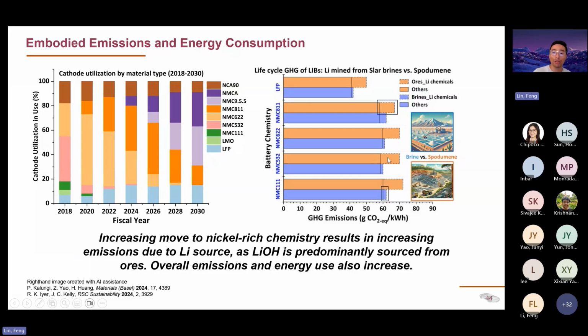But obviously, lithium hydroxide also contributes to more emission, because lithium hydroxide is predominantly sourced from ore, and the overall emission and energy use are higher than from other kinds of sources. So going for nickel-rich, we already have one penalty, the use of lithium hydroxide. If we can use lithium carbonate, that would be great. We are also trying to find ways to use lithium carbonate.